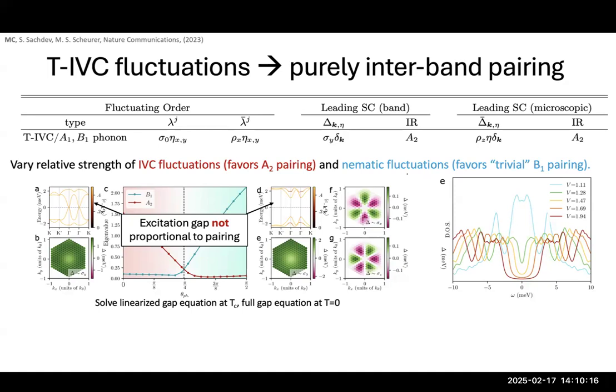And so if we compare this to what's been seen in the trilayer system, they actually see some evolution between doping nu equals 2 to nu equals 3 from a V-shaped gap to something that becomes more U-shaped. And we want to argue that you don't need two separate superconducting states to explain this, that you can have a transition where your spectral properties change and you have the same symmetry on either side of the transition due to these interband pairing effects.